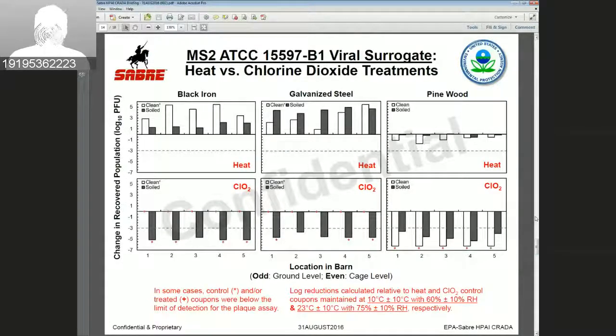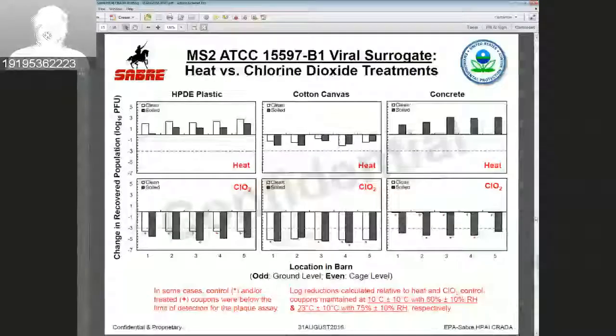Similar thing on the next slide for the MS2 on the plastic, canvas material, and then the concrete. For the heat treatment process, we did see a little bit of reduction on the cotton canvas and then a 3 to 5 log reduction with the chlorine dioxide. That was one of the challenges, keeping the control concentrations up during the 7 days. There was a natural degradation just by holding them in the environmental conditions of 10 degrees C with 60% humidity.